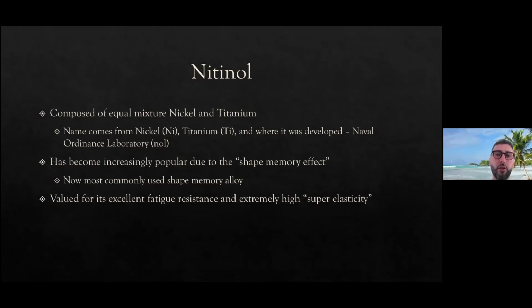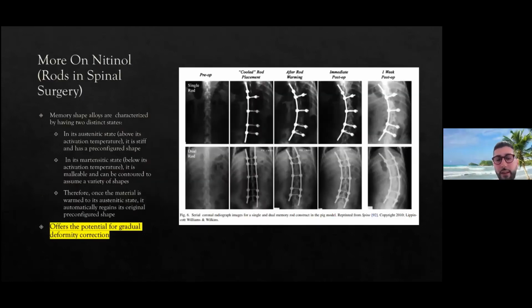And basically, this is what's called a shape memory alloy. So it has fatigue resistance and what's called super elasticity. So basically, and I'll explain this picture in a second, these shape memory alloys have two distinct states, what's called the austenitic state and the martensitic state. So basically, when it's above its activation temperature, so in other words, when it's hot, it has a pre-configured shape and it will always take that shape. But when it's cold, it's malleable and can be contoured.